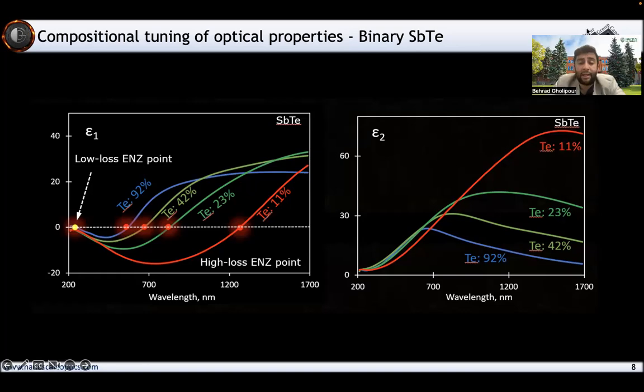So you can see here that I've just taken one of the alloys, again antimony telluride, as our case study, and by changing the composition of tellurium between 92 and 11%, you can change the plasmonic band of this material, and by definition also the losses, the absorption levels that the material enjoys across the visible, near IR to telecom band. This is a drastic change that we can induce by just changing the composition. So really, we're not at the mercy of whatever's on the shelf. By changing very carefully the composition of these different alloys, you can create vastly different materials that are very targeted to the wavelength of operation at which you intend to use your device.